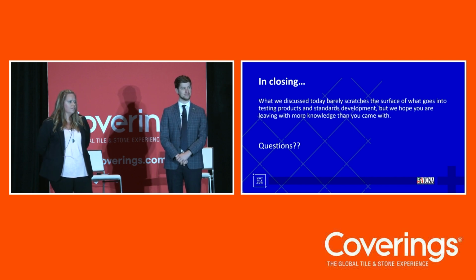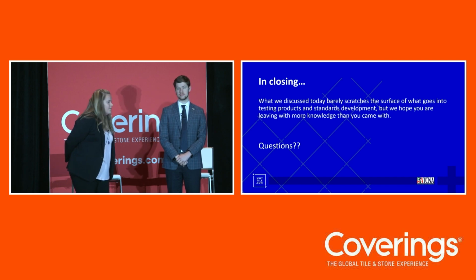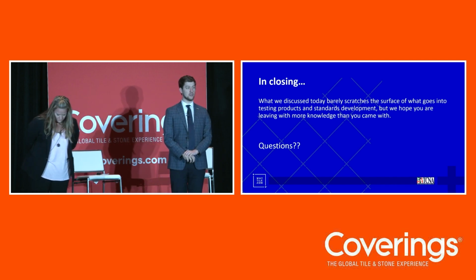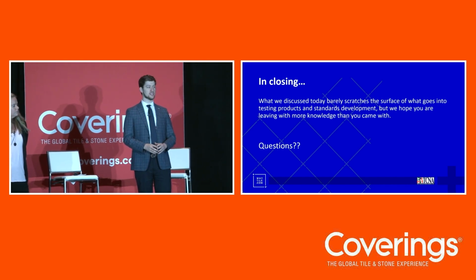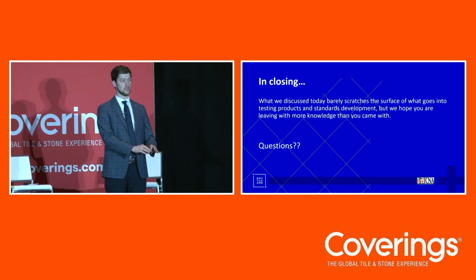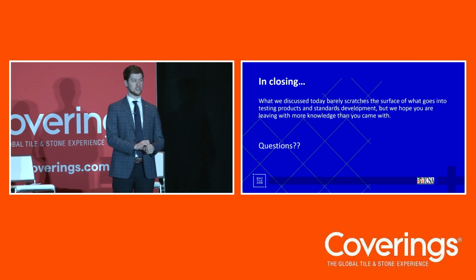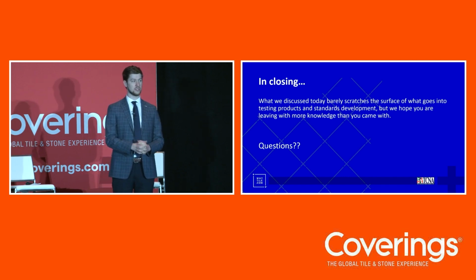On the DCOF, you've got a standard of .42. Is that a standard for interior or exterior? Or are you going to be changing it for exterior because the environments are different? As of right now, the standard doesn't, in any of the normative language, address exterior. There's some informative language, which is not a requirement of the standard, but the .42 does not apply to that. It just applies to level interior spaces expected to be walked upon when wet. The wet DCOF of .42 applies to those.